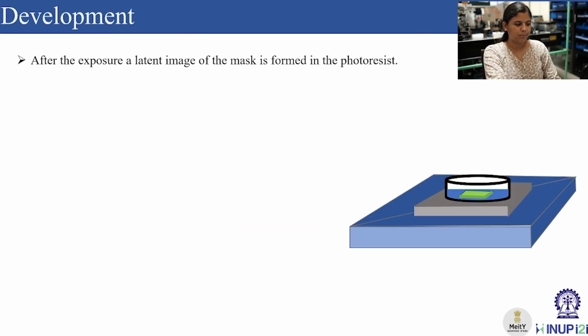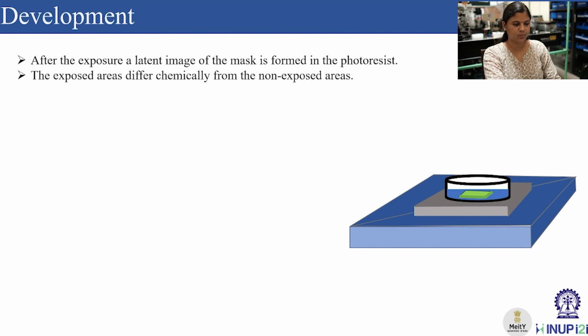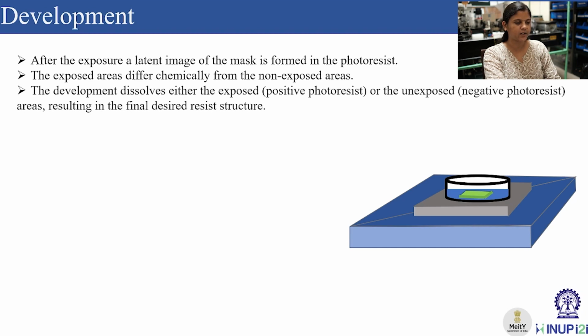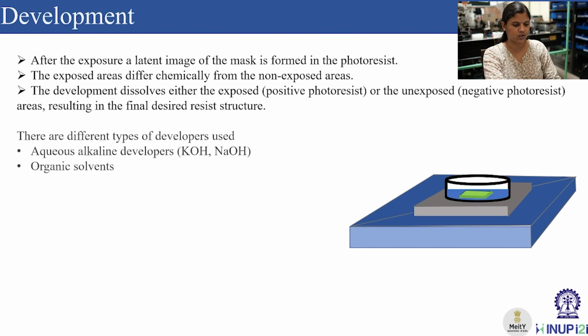So the next step is development. After the exposure, a latent image of the mask is formed in the photoresist. The exposed areas differ chemically from the non-exposed areas, and development dissolves either the exposed areas for positive photoresist or the unexposed areas for negative photoresist, resulting in the final desired resist structure. There are different types of developers that can be used, for example, aqueous alkaline developers like KOH or NaOH. In our lab, we use KOH, and some organic solvents like ethanol, acetone, etc. can also be used.